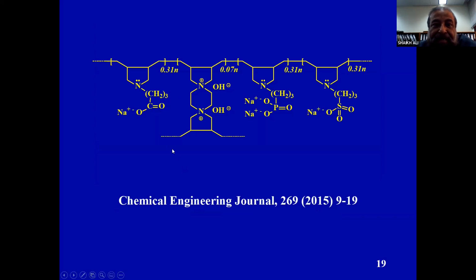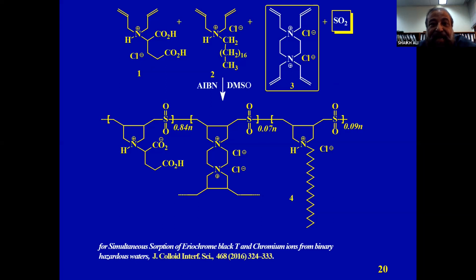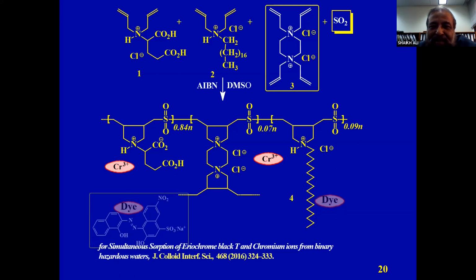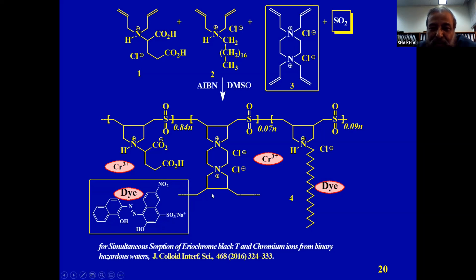Now here, this one, we see they have all three functionalities, CO2 minus, phosphonate, sulfonate. They are all chelating motifs that can capture priority metal contaminants. And here is another one. You can see that it has a glutamic acid residue, and it has a hydrophobic pendant, and they can simultaneously trap chromium and eriochrome black T, EBT, that is also a dye. And here is the chromium coming, and this is how the dye comes in, and we can remove them.